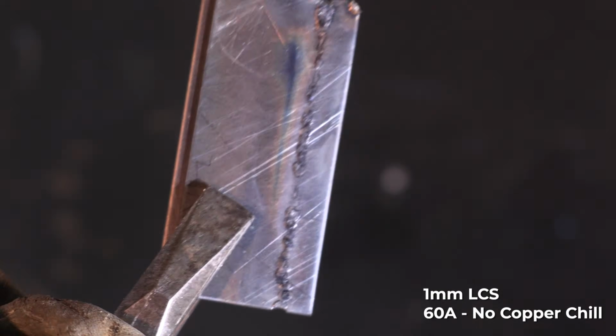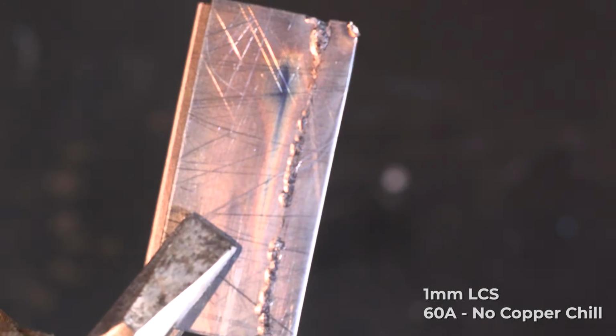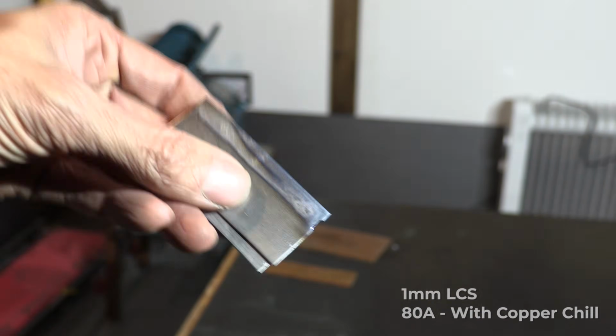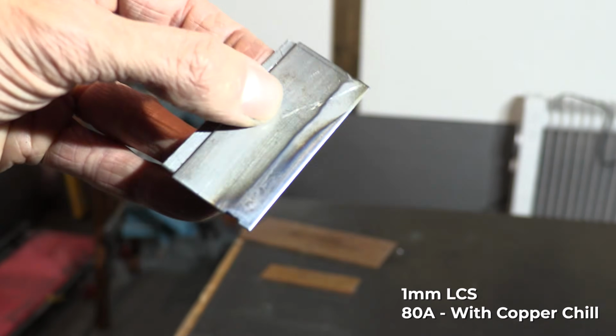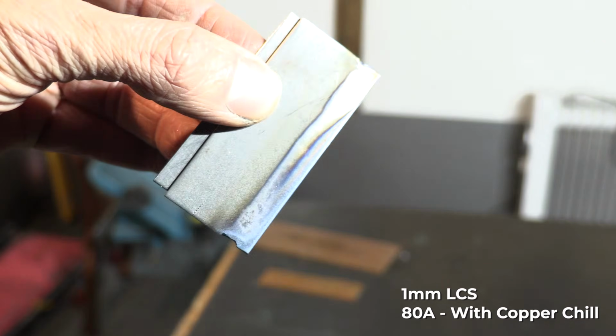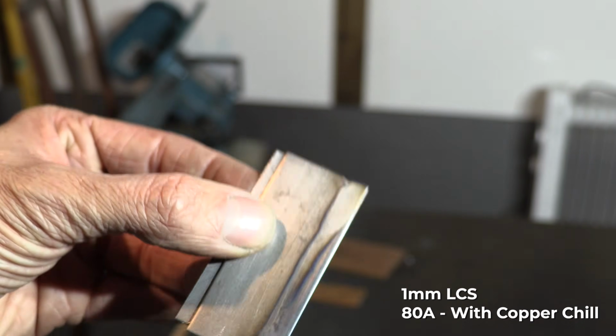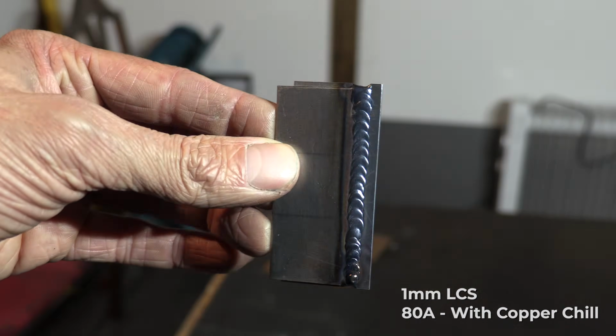Looking at the underside of the welds makes this even more obvious. On the 60 amp weld with no copper, you can see full penetration. In fact, the weld metal has actually dropped through the base of the joint. In contrast, the 80 amp weld made with copper chills shows no burn through, minimal penetration at the base, and also a much smaller heat affected zone. This demonstrates how effectively copper chills control the heat input and the overall weld quality when used correctly.